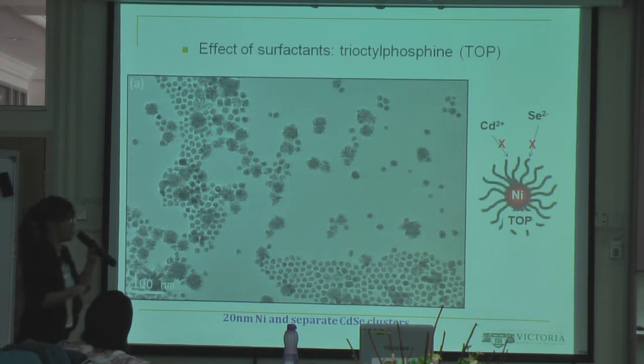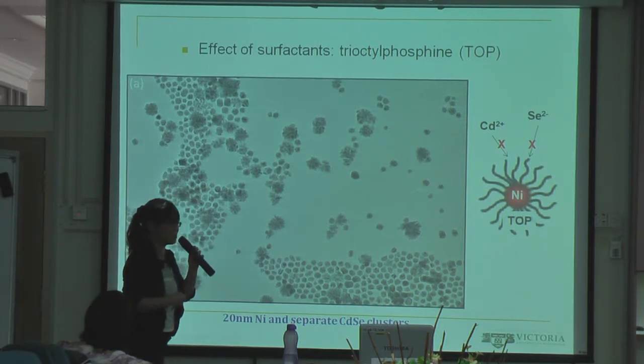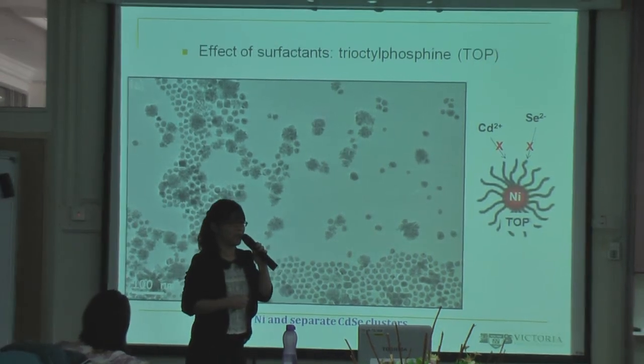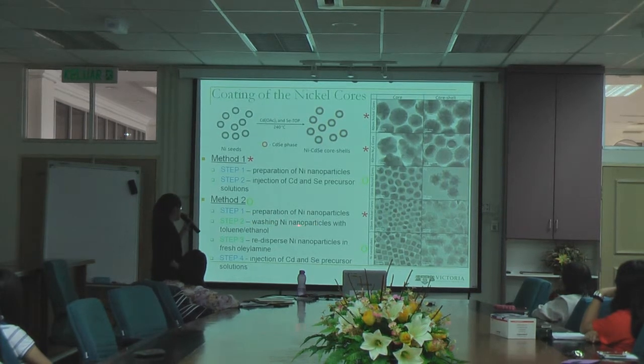At that time, I remember I tried quite a number of things, and one of the things that worked well was to add 2 more steps to the preparation process. So one of them is the washing of nickel nanoparticles with toluene and ethanol to remove the excess trioctylphosphine and to redisperse the nickel nanoparticles in fresh oleylamine before the injection of cadmium and selenium precursor. When these 2 extra steps were applied, these 3 types of nickel particles could be coated with cadmium selenide successfully.